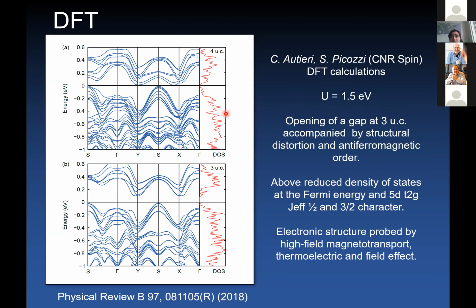So antiferromagnetic order is essential in order to stabilize the insulating phase. Without antiferromagnetic order at a DFT level, the system remains a metal. The density of states that is observed at the Fermi level is quite interesting. So you have a superposition of J effective 1/2 and 3/2 character of the bands, and the coexistence of both electron and hole bands. And we studied very systematically the electronic structure for thick films, where everything was consistent with this picture.